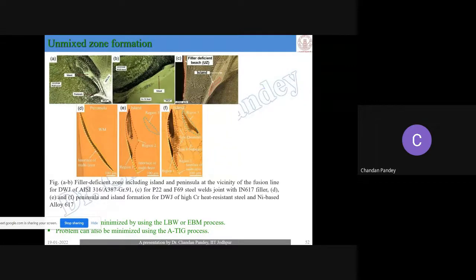That occurs mainly due to the variation in composition of your filler metal and your base metal. So in that case, some portion of the base metal gets melted but remains unmixed with the weld metal and comes in the region of your weld metal. So that again creates heterogeneity. This is the region of your base metal that comes in the region of your weld metal. If the region is directly attached with the base metal, then that is called a peninsula. And if it gets terminated from that point, then it is called an island.